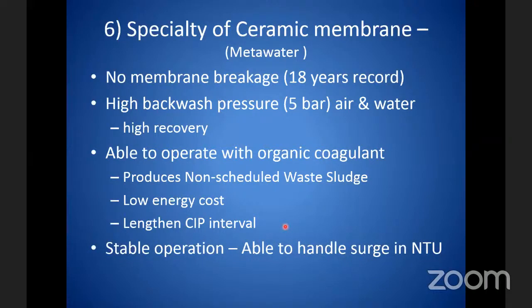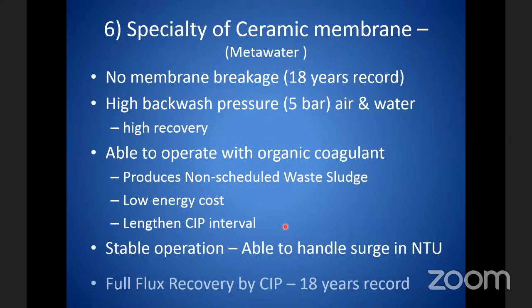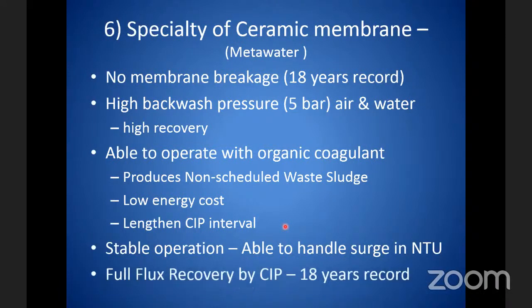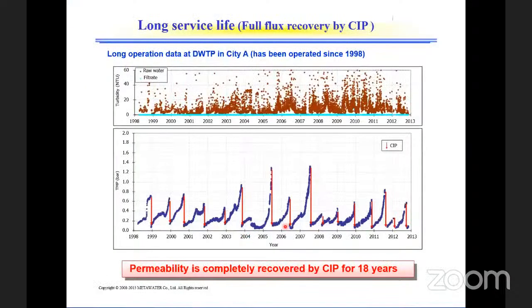It is stable in operation, able to handle surges in NTU. It has had full flux recovery for the past 18 years. Here it shows a record for the Metawater ceramic membrane, that they can get back the flux even after 18 years. Normally with a polymeric membrane, after a while the flux will decline at the same pressure. But this one has been stable for the last 18 years, because with the ceramic membrane you can use very strong chemical, acid or alkaline or whichever, or oxidant, to wash it.